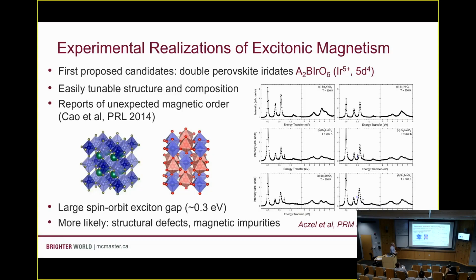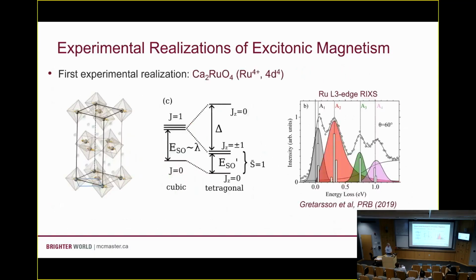So what we think is that any of these reports of unexpected magnetic order are likely coming from structural defects or magnetic impurities. Okay? So one of the things that you can get in the structure is anti-site disorder, which can play around with your oxidation states. So double perovskite iridates, not the way to solve this problem.